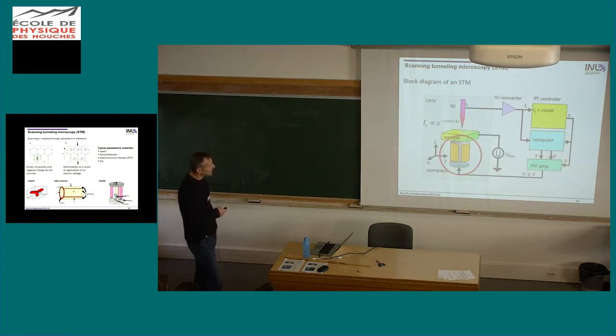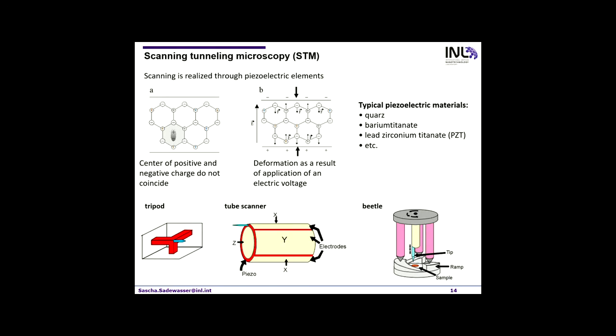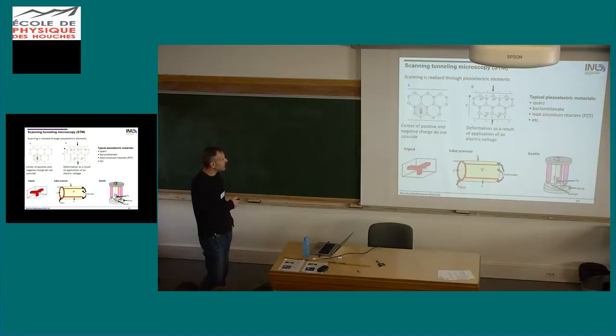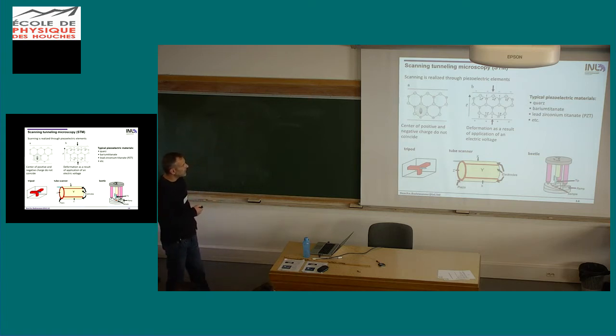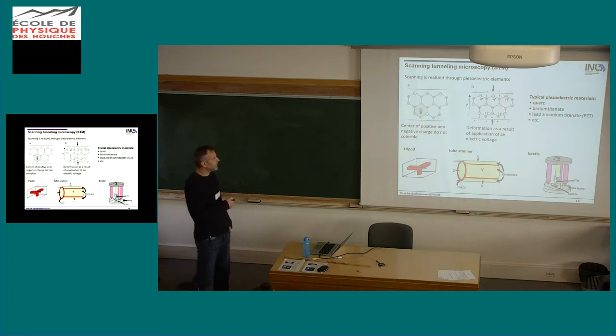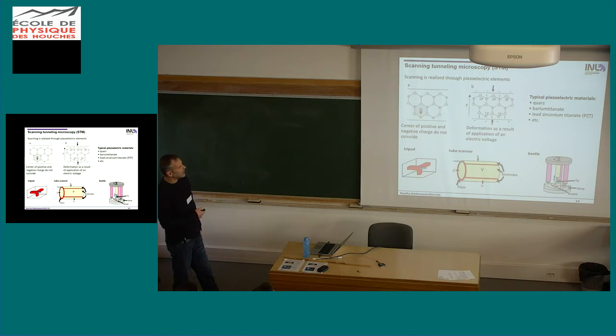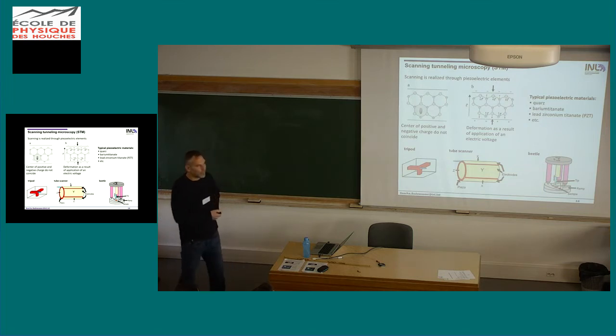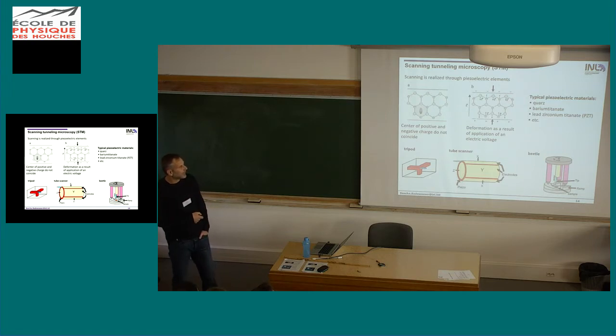So the next ingredient is the piezo. Piezoelectric elements or materials are characterized by having a different center for positive and negative charges. So in the crystal structure, they don't coincide. As a result of this, you can either apply a bias, and then you get a mechanical deformation of the material. So this is what we use. Or the other way around, you can apply pressure to your material, and then you get a voltage. But here we use the deformation as a function of applying a voltage. And typical materials are quartz, and then what's mostly used is lead zirconium titanate.